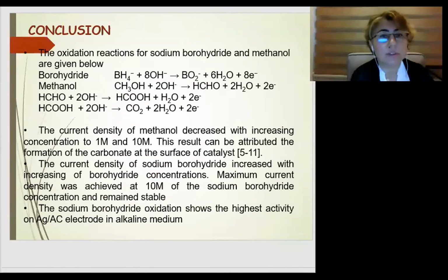You see here the oxidation reactions for sodium borohydride and methanol, and the current density of the methanol decreases with the increase in concentration from 1 molar to 10 molar. These results can be attributed to the formation of carbonate on the surface of the catalyst. The current density of the sodium borohydride increased with increasing borohydride concentration. Maximum current density was achieved at 10 molar sodium borohydride concentration and remains stable.